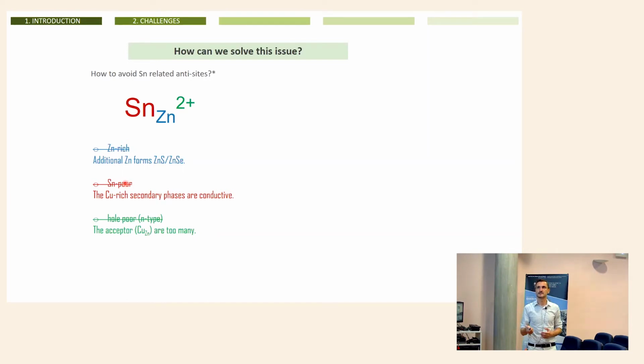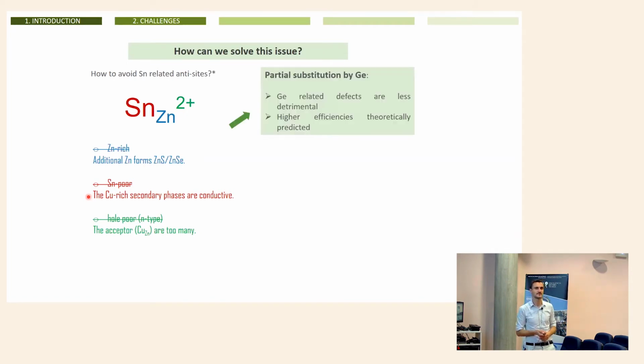Another possibility is to produce a tin-poor compound, but this implies that normally copper-rich secondary phases are produced and are very conductive, and this really kills your material. So the tin-poor compound doesn't work at all. The other possibility is to have a hole-poor N-type material forming this kind of acceptors. But normally this is uncontrolled and you cannot work with hole-poor N-type conditions. Thermodynamically, it's very difficult. And also in addition, in the thin film community, we are very good at making solar cells with P-type absorbers, but we are extremely bad with N-type absorbers. So normally with an N-type absorber, we don't know how to prepare an efficient solar cell. In all thin film solar cells, the absorber, the heart of the solar cell, is a P-type semiconductor.